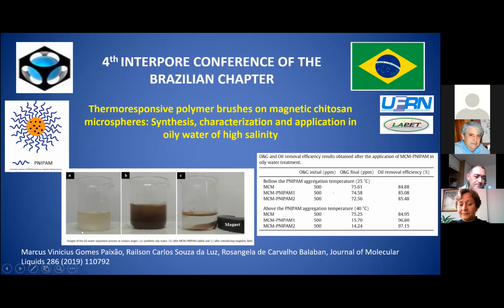Here you have our oil water, petroleum. We always use petroleum as oil phase. So you have our oil water of high salinity. And in vial B, we added the microspheres of chitosan containing the magnetic particles and finally applied a magnetic field. So it was possible to concentrate the oil inside the microspheres and to separate it from the aqueous medium.